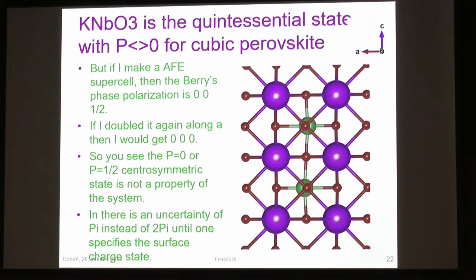So I actually found, just by fooling around, that I can make a zero polarization centrosymmetric potassium niobate by making an antiferroelectric structure. It turns out you stick this in Quantum ESPRESSO, calculate the Berry's phase polarization, you get 0. So then David asked me yesterday, what happens if I deform this and make everything on the cubic lattice? Well, it turns out if I take this doubled cell and do that, I also get 0. So just like in the sodium chloride case, I can get for cubic perovskite potassium niobate both 0 and the half a quantum lattice results within DFT.